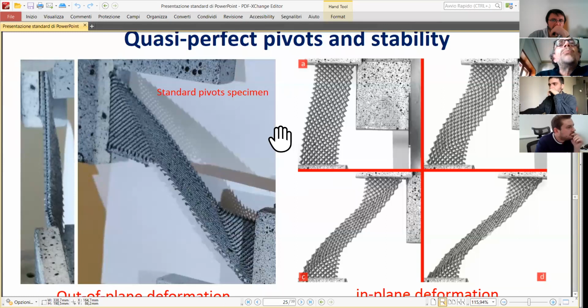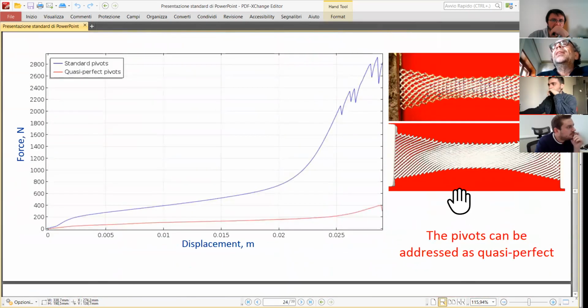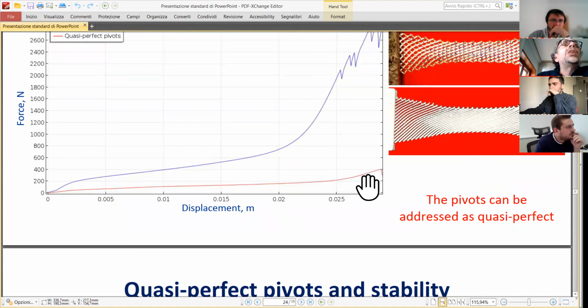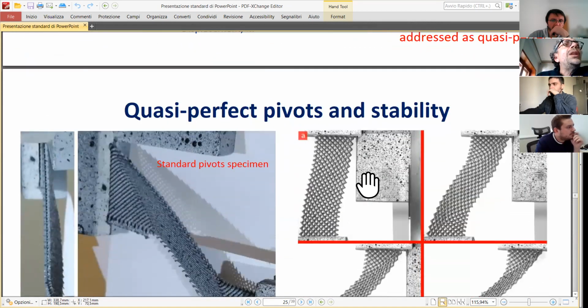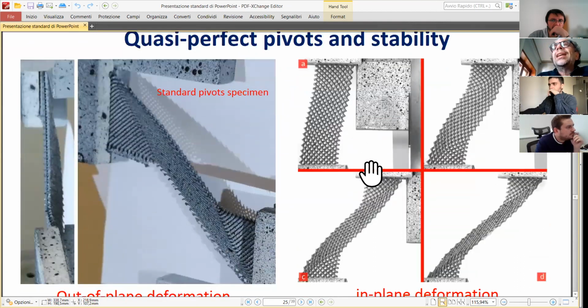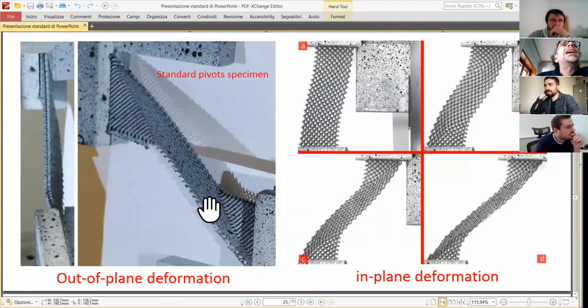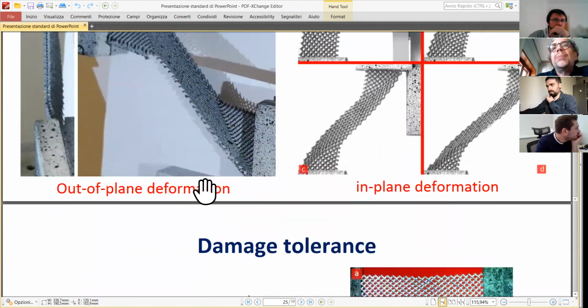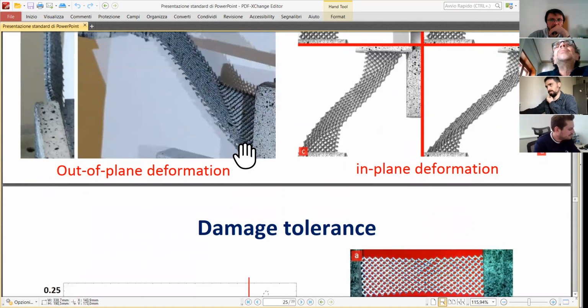Now, somebody told us that this specimen is behaving very well, but it is useless because it could buckle, it could not resist in shear. So we developed shear tests, again in Berlin, and this is a very nice pattern of deformation. As you can see, this specimen still behaves as a second gradient material also in shear deformation. The only problem is that sometimes this material buckles, okay? So it gets out of the plane of deformation, but in a way which is not catastrophic, and by the way, totally described mathematically.